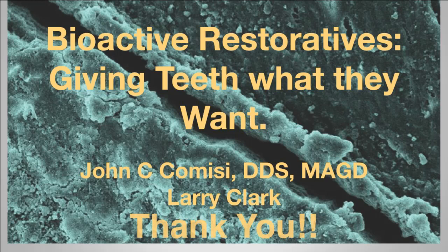Make sure that you know what the energy level of your light is to make sure that you're getting proper cure. Even though this is a dual cured material, it does take several minutes for that dual cure activity to occur. So please light cure it properly or allow it to set in the tooth for the appropriate amount of time, which is 3 minutes at body temperature for it to completely set. If you remove the band or you don't give it the opportunity to set completely in the dual cure phase, you will have mush. That's not a good thing. So make sure that you allow full curing to occur. That's really very important. But there is time saving and there's money savings as well because you don't have to worry about bonding agents typically.